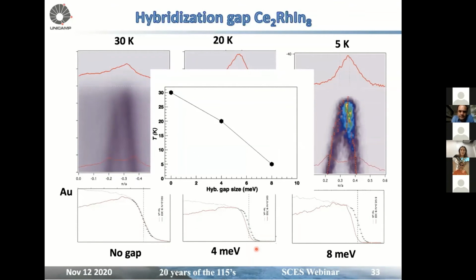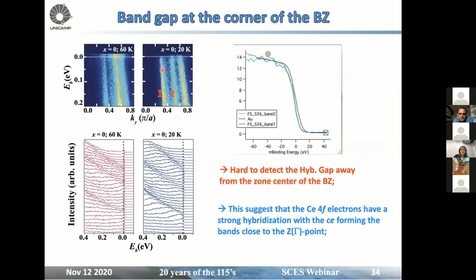And then if I play around the Brillouin zone, I don't see a big gap at any other places. I'm showing you here at the corner of the Brillouin zone. And so that suggests that the 4f electrons have stronger hybridization with the conduction electrons that form the gamma and Z point, as already discussed in Professor Kotliar's paper on the 115s, that the CeIrIn5 is hybridizing more with the indium out of plane.